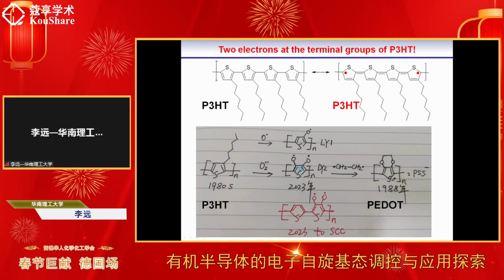Recently, we prepared this kind of radicals, which we named LY1 and LY2, and we submitted this paper to Science China Chemistry, and we're waiting for the news. And we think this kind of open shell polyradical will be very important for this field. I believe that the conductivity of this polymer can be comparable with PEDOT and much higher than P3HT, because the P3HT and PEDOT show different types of radical. You can see the diradical character of P3HT, while we know PEDOT is the radical cation type of doped polymer.